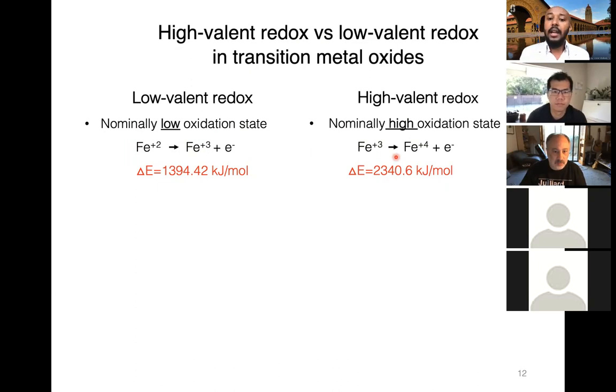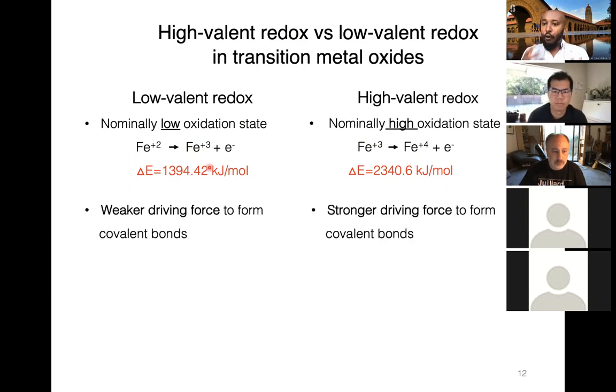And as you can see, the energy required for this process is higher than for the low-valent redox. Because of such a difference in energy, when you put this energy in to involve high-valent redox, the material tries to respond to become stable by forming a short covalent bond. In other words, there is a stronger driving force to form a short covalent bond in high-valent redox systems as opposed to low-valent redox systems.